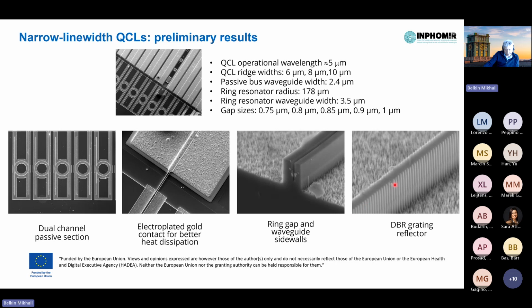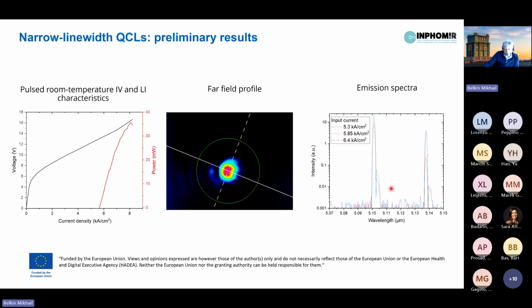By adjusting the DBR coupling strengths and position, we could select only one of the two and operate the device at just one single wavelength. Measurements of the line widths are subject to development of the CW laser at room temperature. Once this is done, we will be able to confirm our calculations that the line width of this device is indeed reduced by 50 to 100 times. Far field profile is close to TEM00.